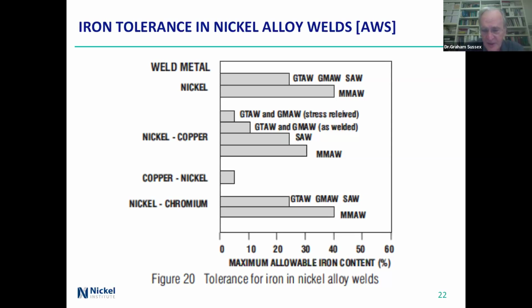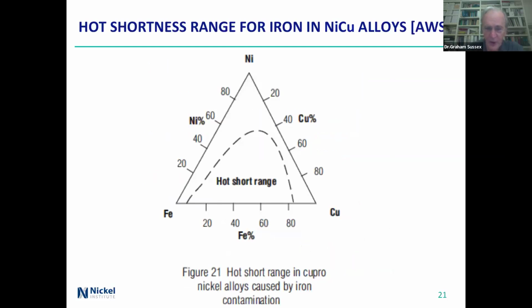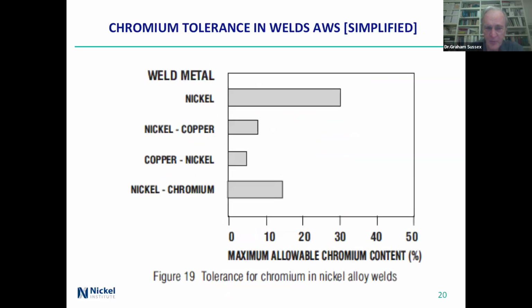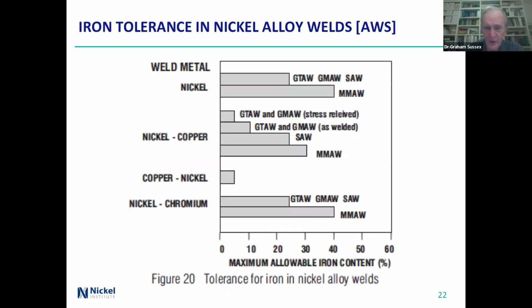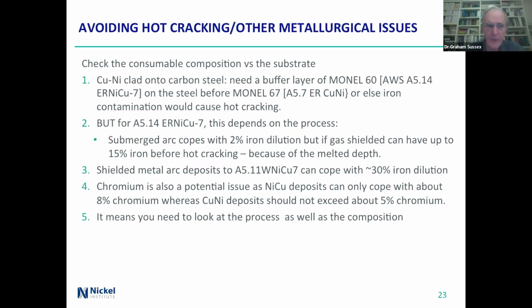And again, this is for iron content. The previous one was for iron content, and up here we've got chromium content. So they're also potentially a problem. So that's summarizing those bits. It means that you need to check the consumable composition versus the substrate.